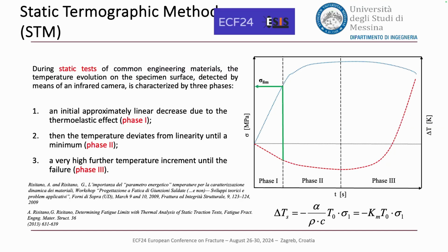The transition between phase 1 and phase 2 will be the sigma limit, that is a good estimation of the fatigue limit. I want to specify that this method, the static thermographic method, is still an object of research. It is well established for metallic materials, but not for composite. So in this study, we are trying to apply the static thermographic method also on composite.